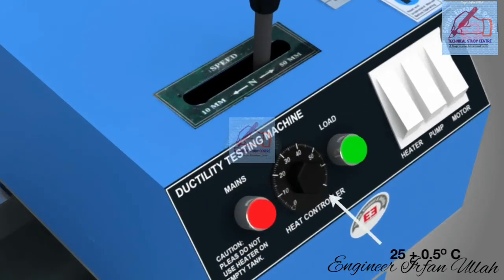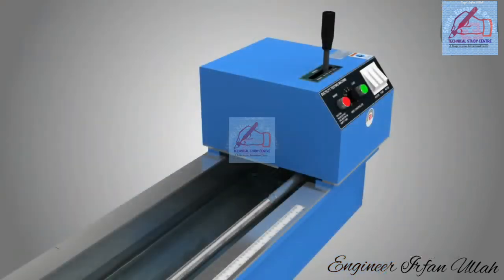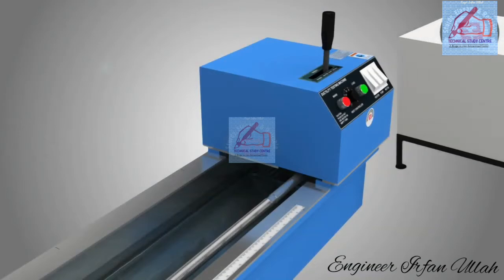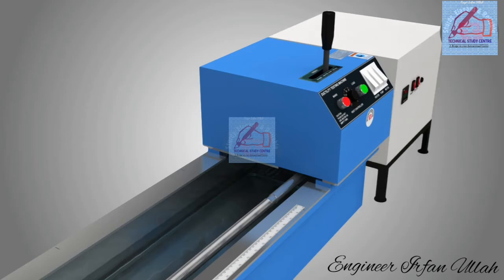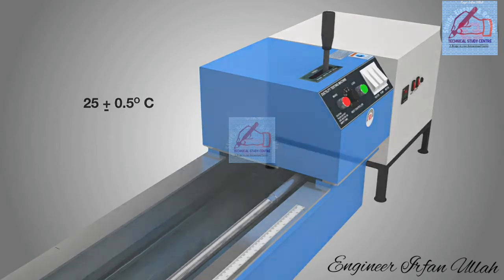The heater is provided for maintaining the required temperature of 25 degrees Celsius plus or minus 0.5 degrees Celsius. Also, a refrigeration setup with compressor and other fittings is recommended to carry out the test at the required test temperature of 25 degrees Celsius plus or minus 0.5 degrees Celsius.